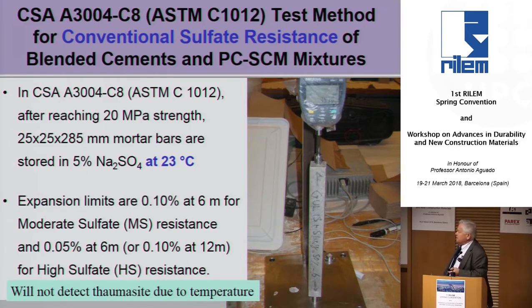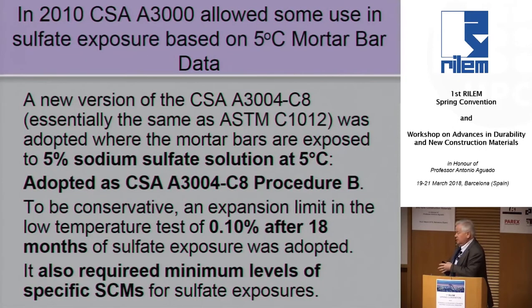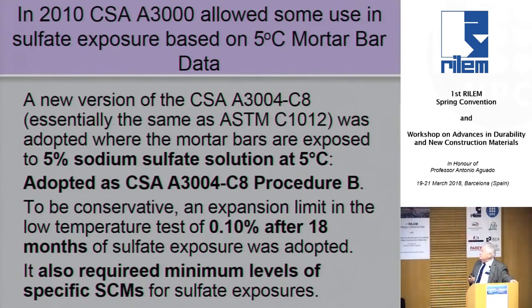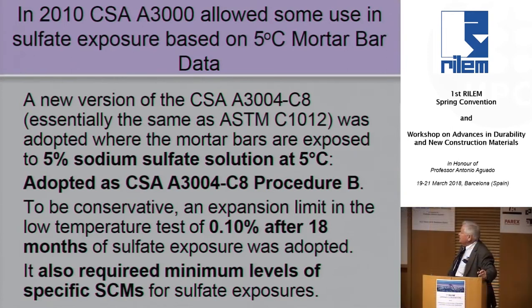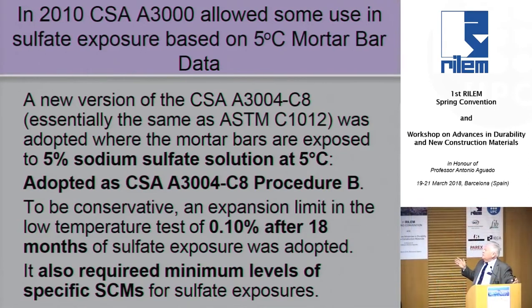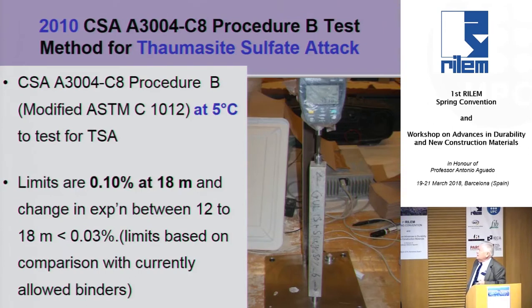But with Thaumasite, we're thinking, well, what do we do about this? So we developed another mortar bar test at cold temperature. We put them at 5 degrees. Basically the same test method, but storing them at a lower temperature. And so we adopted this as a way of moving forward to allow the use of limestone cements with supplementary cementitious materials or blended systems in the sulfate environment. And this was in 2010, so 2 years later, we came up with it based on mortar bar testing. That's the test method. It's exactly the same test method except for the temperature.